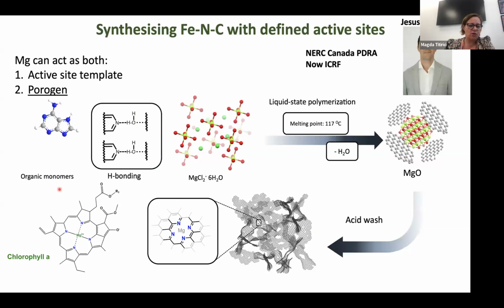So we took an organic monomer. This was 3-aminopyridine, and we took magnesium chloride hexahydrate. What happens during the process is that the 3-aminopyridine interacts via hydrogen bonding with this magnesium chloride hexahydrate. You have a liquid state polymerization. You form some magnesium oxide. This acts as a template to form the porous carbon, but at the same time, some of this magnesium would also coordinate to your nitrogen sites from this 3-aminopyridine. So you would form an organic framework that has this magnesium 2+ coordinated to nitrogens.